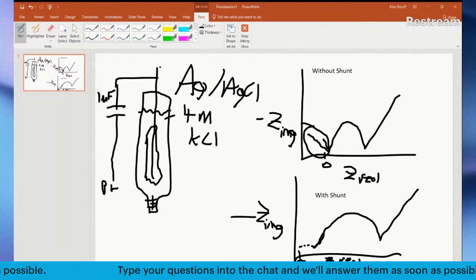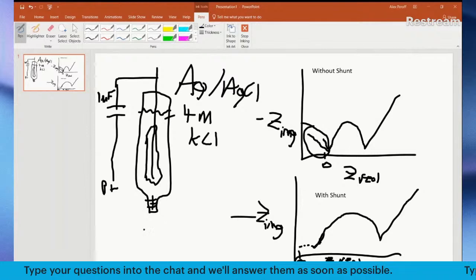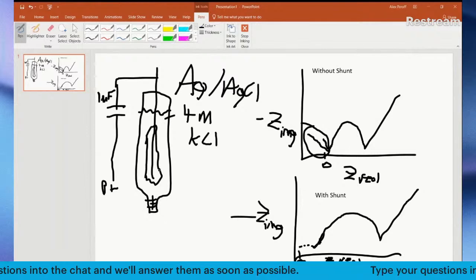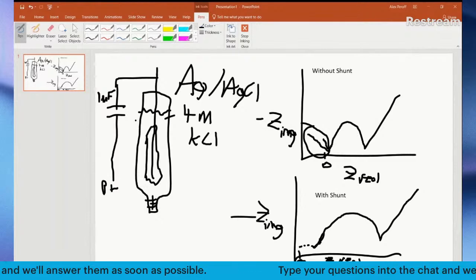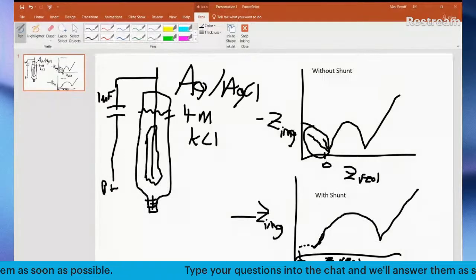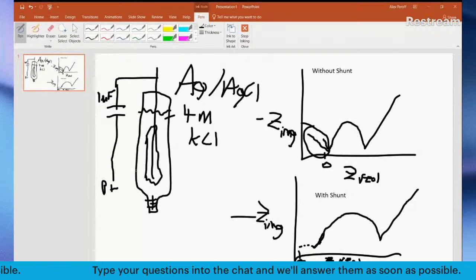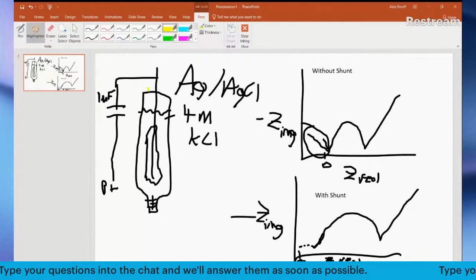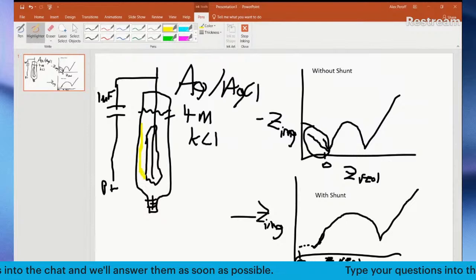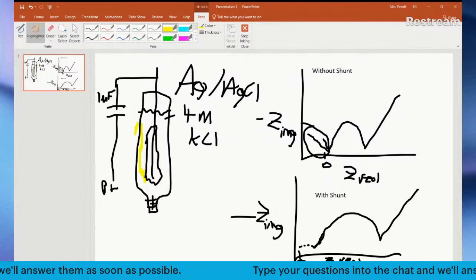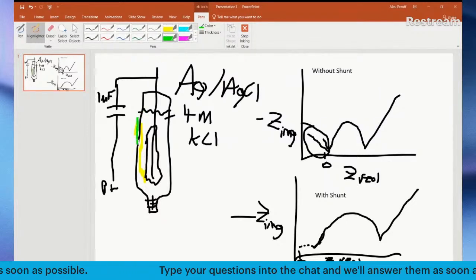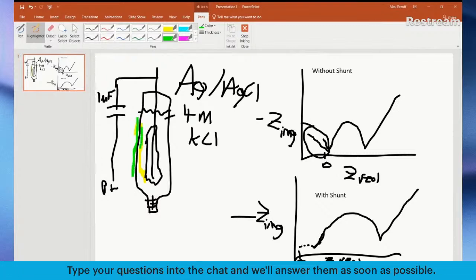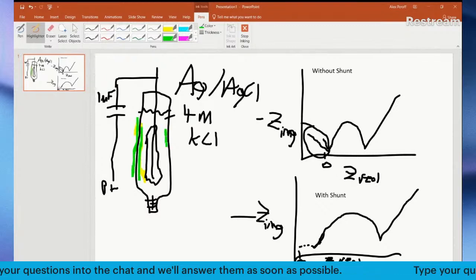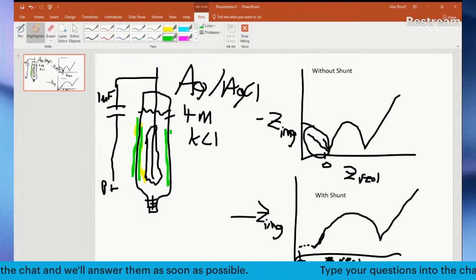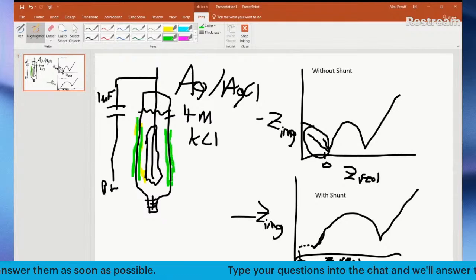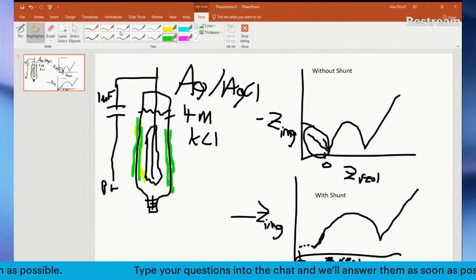And the reason for this mostly has to do with an inherent capacitance associated with this kind of reference electrode. We don't know exactly what it is, but talking to a colleague, we think it's the glass. So there's charge that can build up on the edge of the glass of the reference electrode, and that can create somewhere between 7 and 10 picofarads of capacitance.